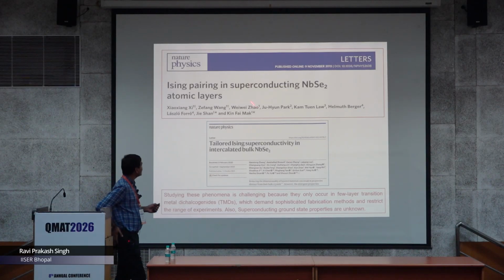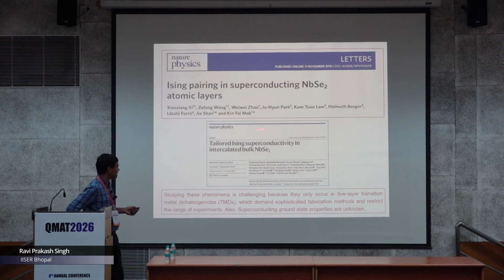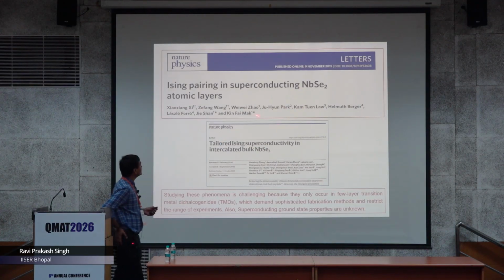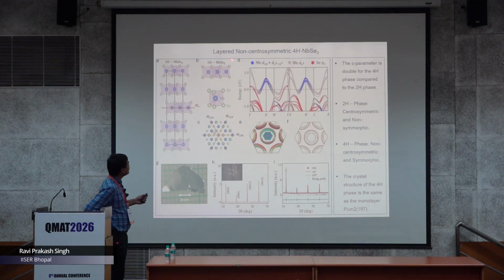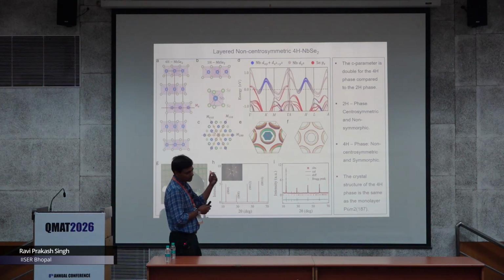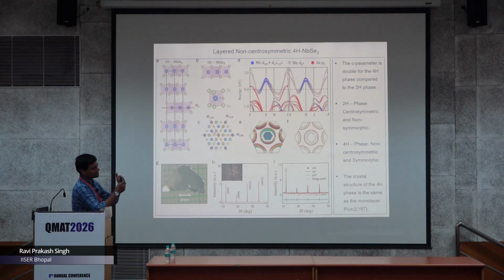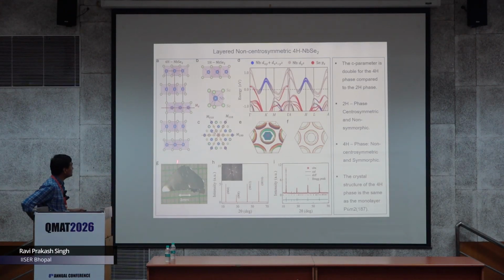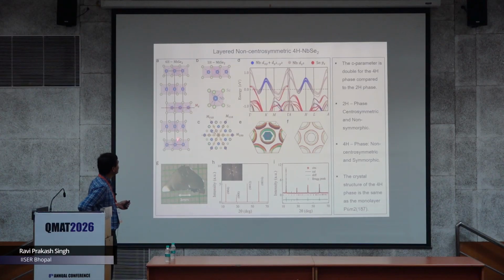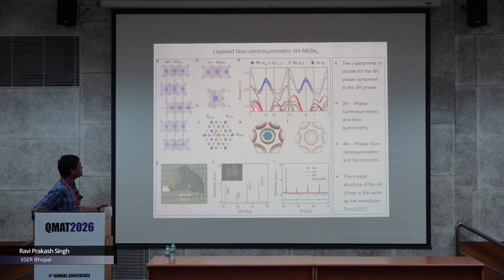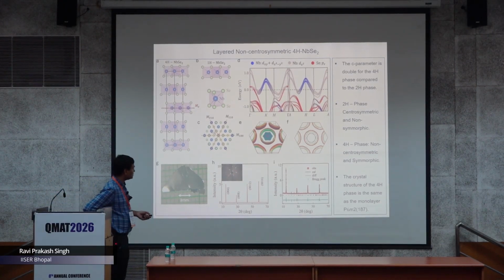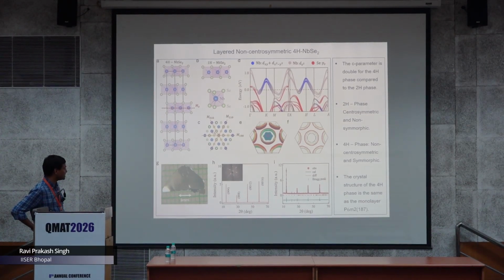But the problem was, Ising pairing was only observed in monolayers of 2H NbSe2. And when we look at the monolayer of NbSe2, it is a non-centrosymmetric one, and it gives you a very high spin orbit coupling, and that basically gives you that very high Hc2 and Ising type of pairing. Then we realized this bulk 4H NbSe2 has the same structure. It is similar to 2H, only one layer is a little bit off, and that is giving you non-centrosymmetricity. This crystal is grown at IISER Bhopal, and it is well characterized. It is a very high quality crystal.